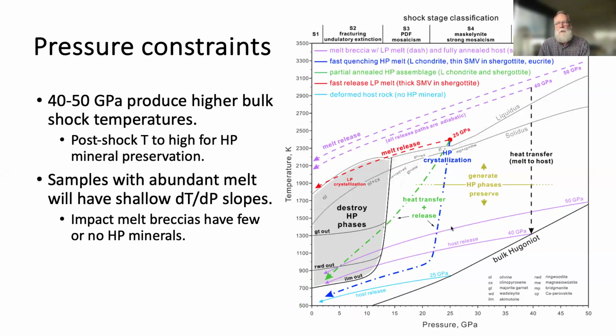This also gives us pressure constraints. So if I shock up to 40 or 50 gigapascals, if I'm up in this range, the minimum temperatures I can get are given by these release paths. So I can't really get under this gray box if I'm shocked to 40 or 50 GPa, right? So if I go from 50 and I take a path something like this, I'm going to end out being in very relatively hot post-shock temperature. The other thing is, if this were the case, the mineralogy of what I produce would be predominantly Bridgmanite, and all of that would be destroyed.